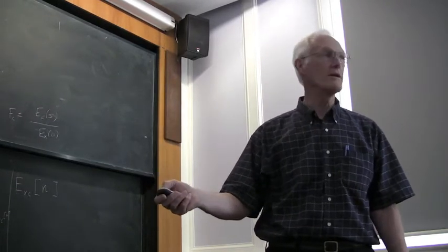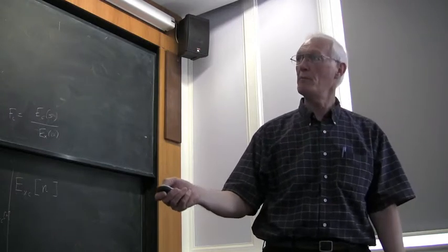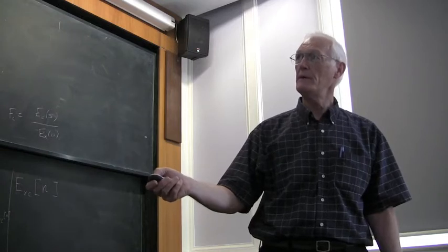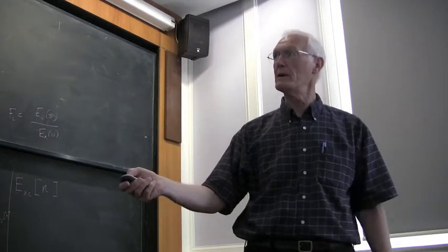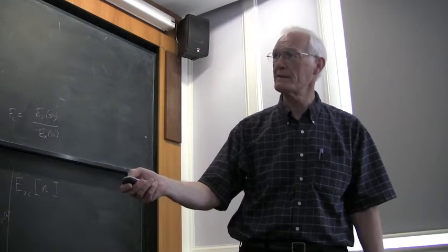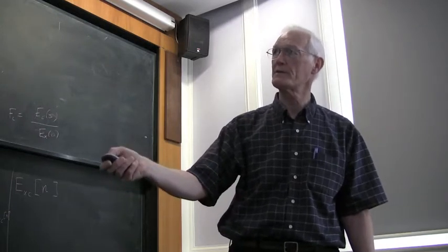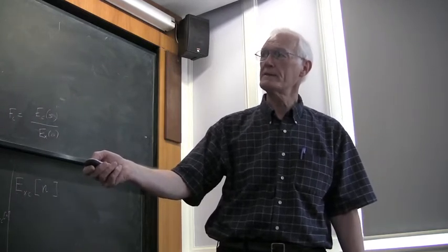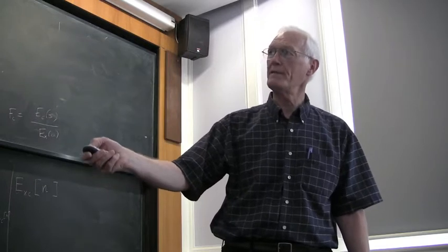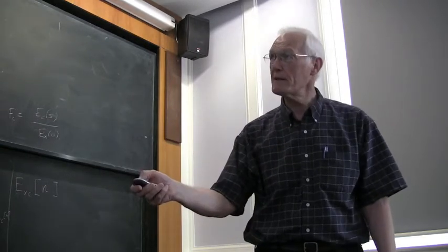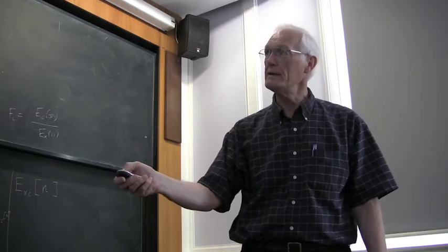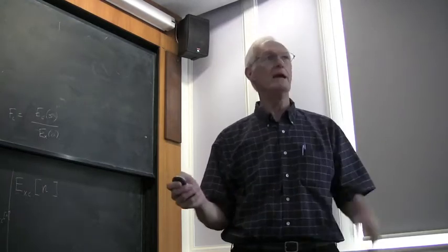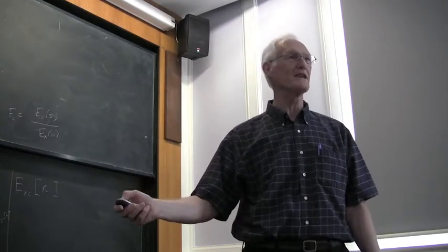And when you get to iron, it's not quite as good. And the moment, you get the iron moment actually rather well, well, I'd say that's very well. But some of the terms are not as good, for example the bulk modulus of calcium fluoride. There you're getting more of a difference between this APW method and the pseudopotential, and that's because the core in calcium is not so deep, and the pseudopotential approximation is not so good. So at that level, we're saying we're not quite getting the same things.